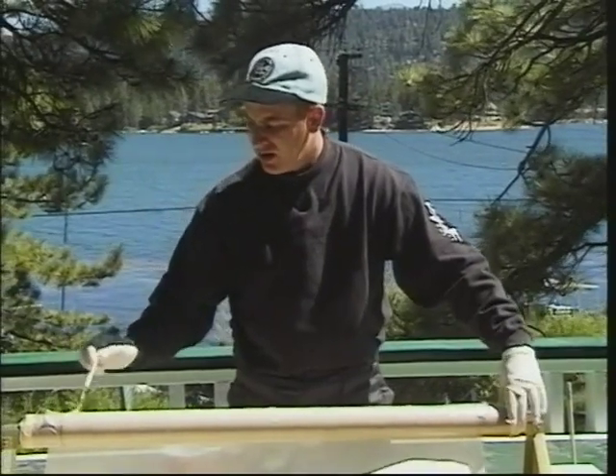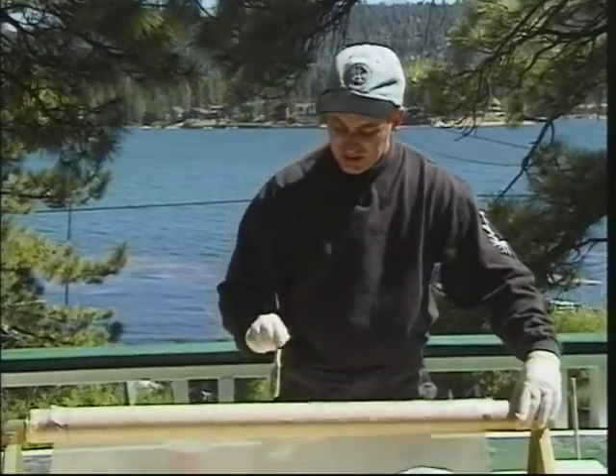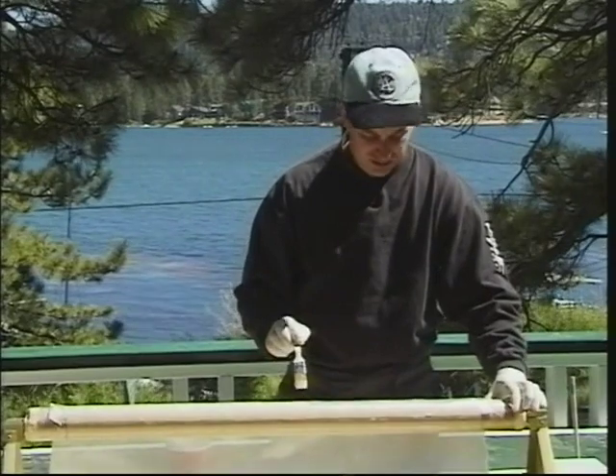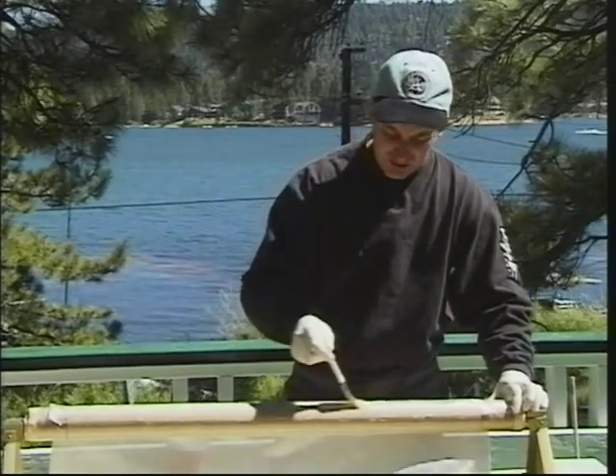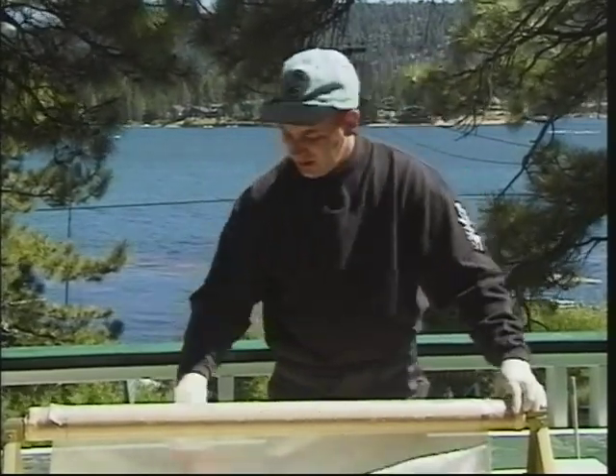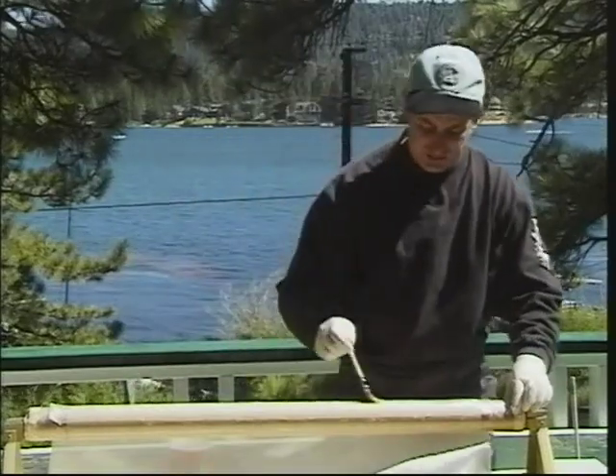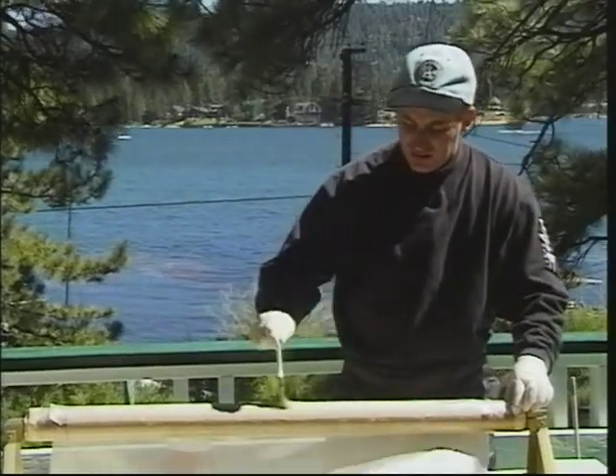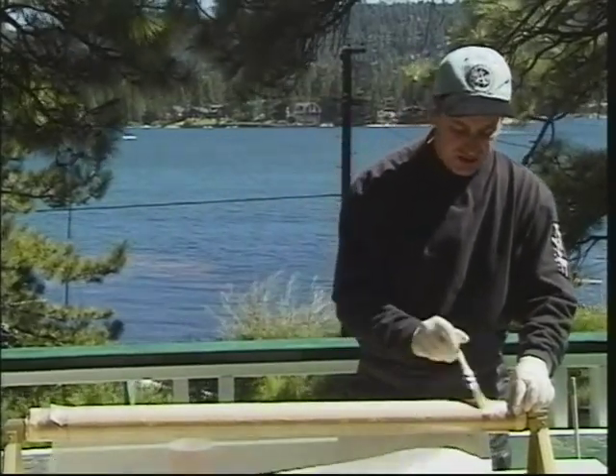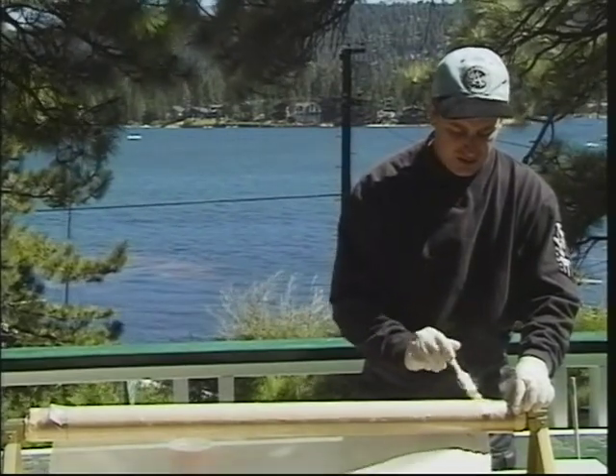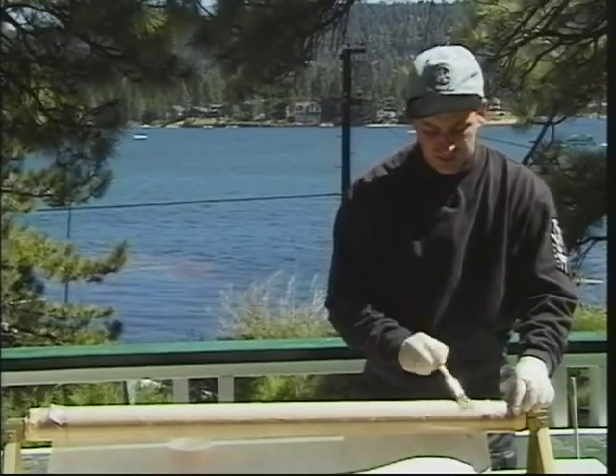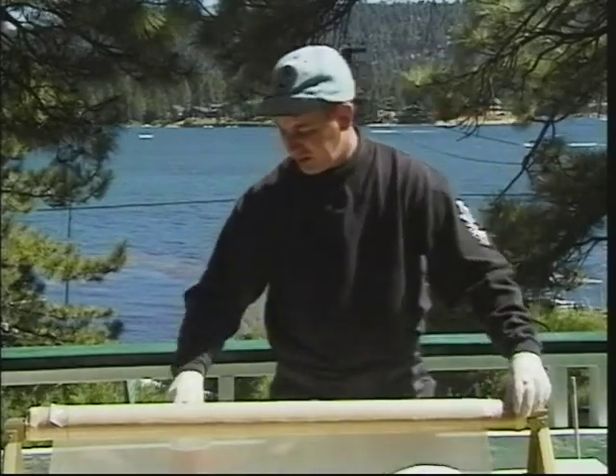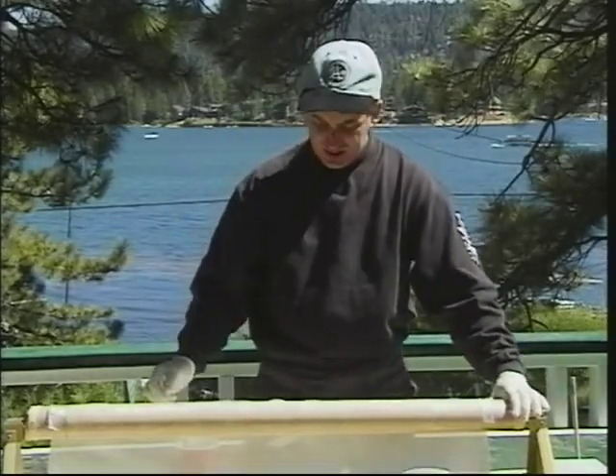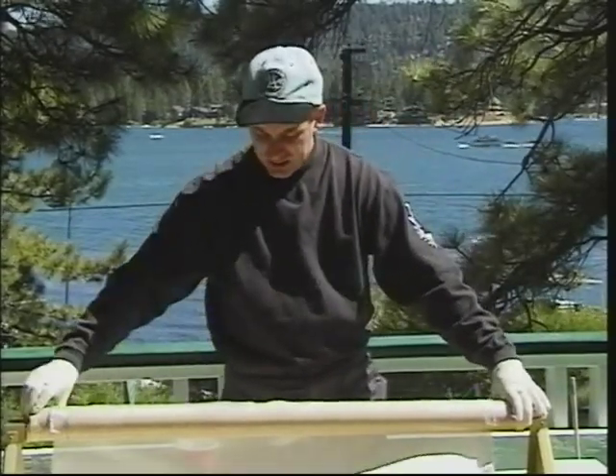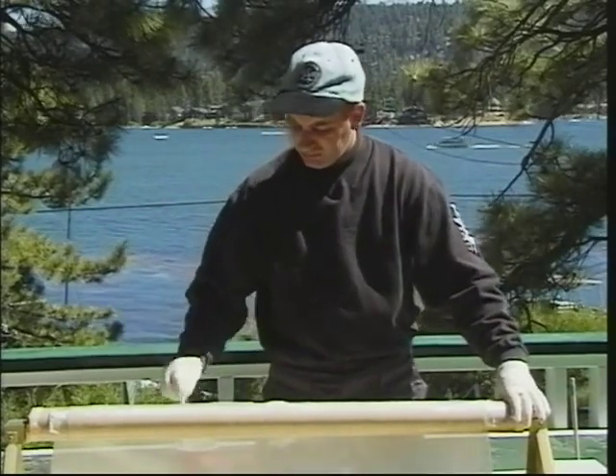Again, you just want to go until the cloth becomes transparent. You don't want to gob on the resin so that it's real glossy on the surface, but just work it along its length. If you get towards those edges, use that rolling technique again so you don't pull up any fibers. And then just use gravity basically to work your way around the tube.